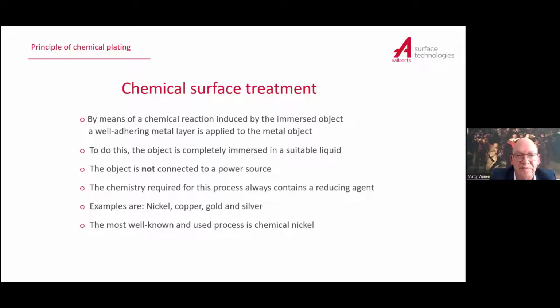chemical surface treatment. The chemistry which you need here always contains a reducing agent. Because your metal is dissolved in the solution, you have to have electrons delivered to your ions, which are metal 2+ ions, which means they miss electrons, to make sure that those electrons go from metal ions to metallic parts. Known examples are nickel, copper, gold, and silver, and the best known, of course, is chemical nickel.